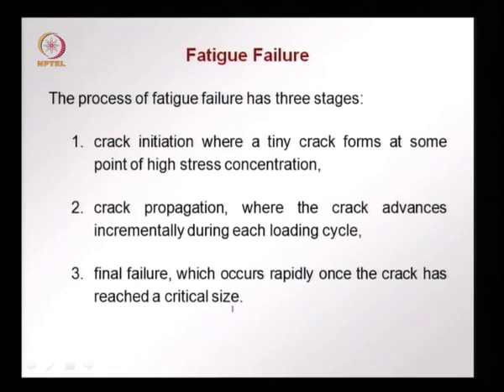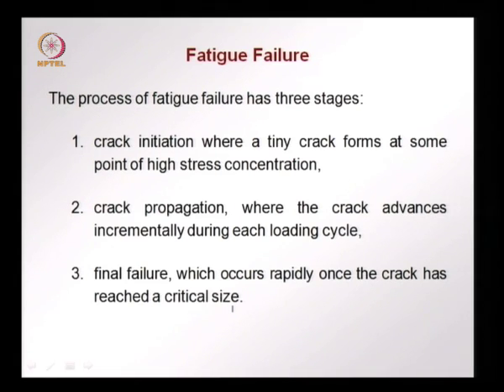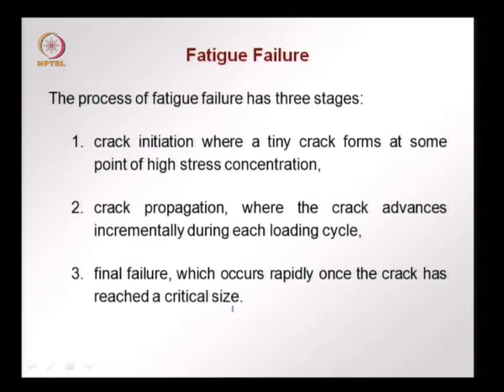The process of fatigue failure occurs in three stages. First, a crack initiates at a defect — a tiny crack at some point of high stress concentration. In the second stage, as the material undergoes cyclic stresses, this tiny crack starts propagating in a stable manner. With each loading cycle, the crack propagates a little bit more. Finally, when the crack has reached a critical size, the stress is high enough to cause sudden brittle failure. So crack initiation occurs first, followed by stable crack propagation, and finally sudden dramatic failure.